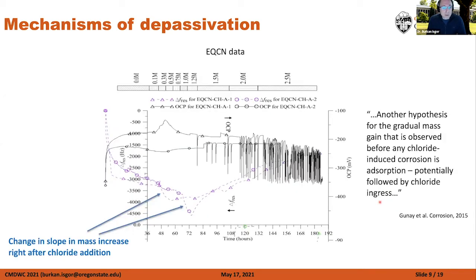Now, when you start adding chlorides, this is basically the data that I just showed you, this purple line here and OCP line here. At one point, when you start adding chlorides, you see something very interesting. There's a sharp slope change occurring in the frequency, and this is actually corresponding to a mass increase. At the time, we tried to interpret this, maybe overinterpret this, I have to admit, to what might be happening to the passive film. This mass increase right after chloride addition and before any pitting starts, we interpreted as absorption of the chlorides on the surface of the passive film.